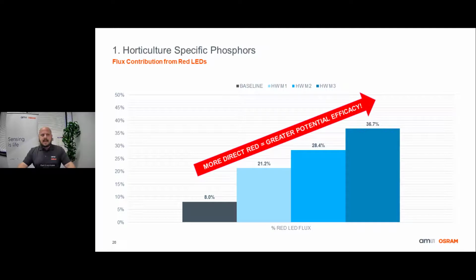So here we can see how using Horti white allowed us to significantly increase the contribution of direct emitting red photons in the spectrum. The direct emitting red only made up 8% of the baseline spectrum, and this severely limits potential efficacy, whereas the Horti white allowed us to increase that contribution 3 to 5 fold, up to almost 37% for the M3 solution. So again, the more direct red contribution, the greater the efficacy we can get.